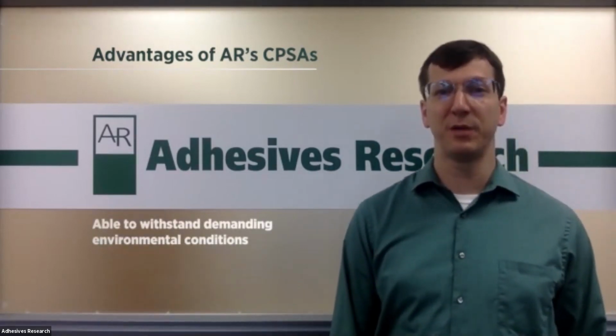Adhesives Research conductive PSAs provide several specific performance benefits as well. They provide precise, directed electrical conductivity. We can tailor exactly where the conductivity is, whether it's isotropic in the X, Y, Z planes, or anisotropic, where we have Z-axis only conductivity. We tailor this design through the selection of specific fillers, including carbon black and other metal particles. And by designing these high performance adhesives, we can get very fine pitch connections, down to 300 microns by 300 microns to make a conductive adhesive bond. We're able to withstand demanding environmental conditions with our PSAs.